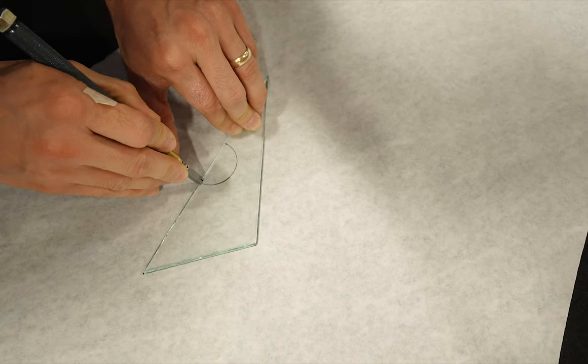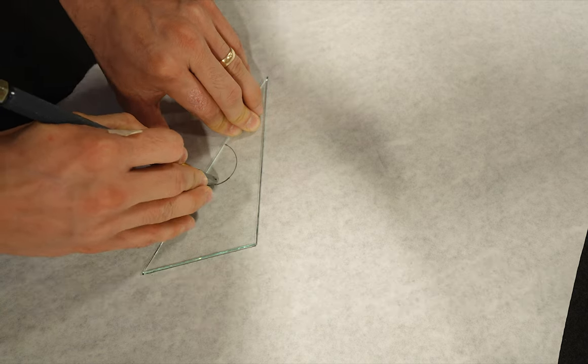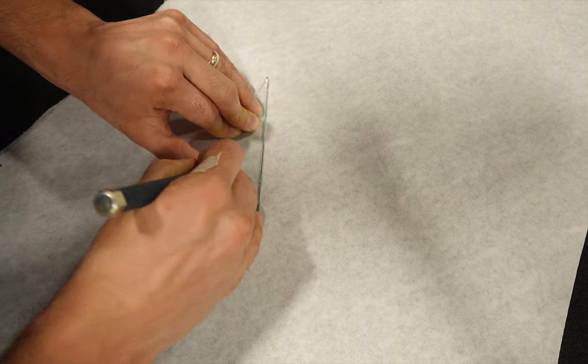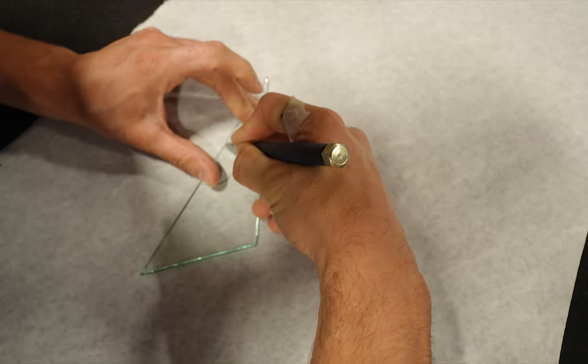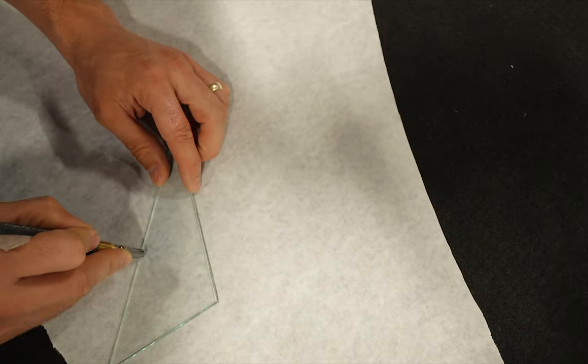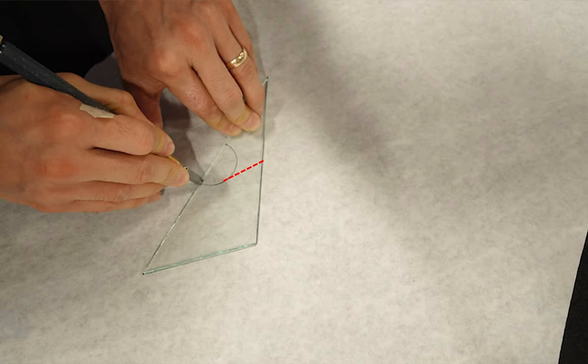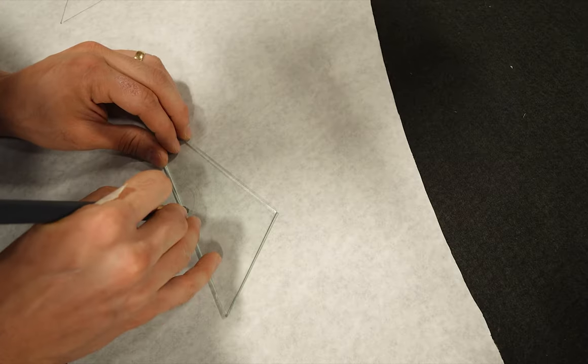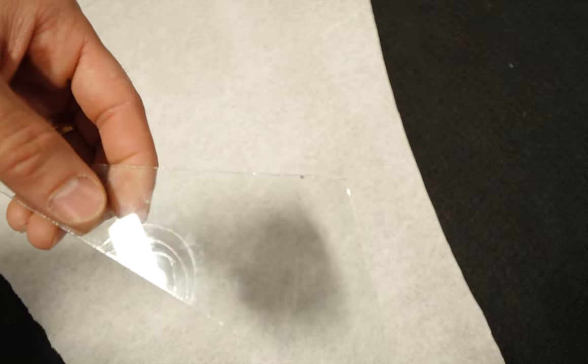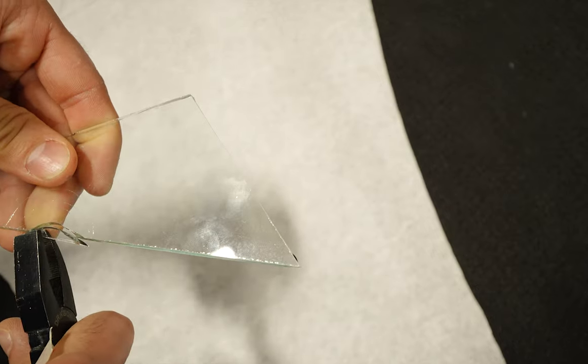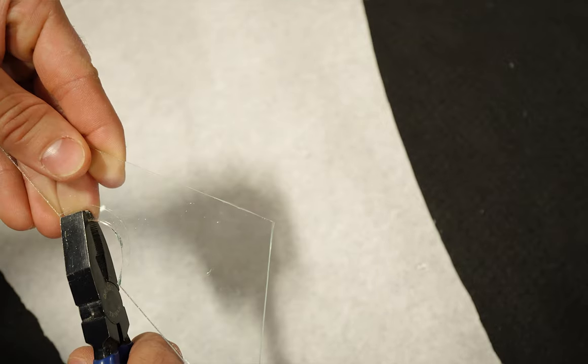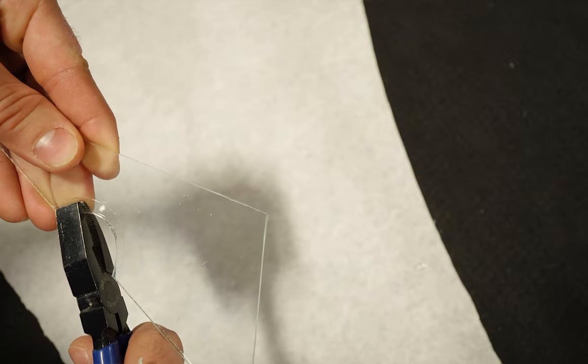Here we are cutting a tight radius. Sometimes when doing complicated cuts like this with a tight radius you will need to do multiple scores. If you try to break the glass with just one initial score you will likely break through along the dotted line seen here. Instead you need to add additional scores within the radius so that you can groze them out individually. This is one of those things that taking your time now doing it the correct way will keep you from needing to re-cut glass and wasting time rescoring the glass.